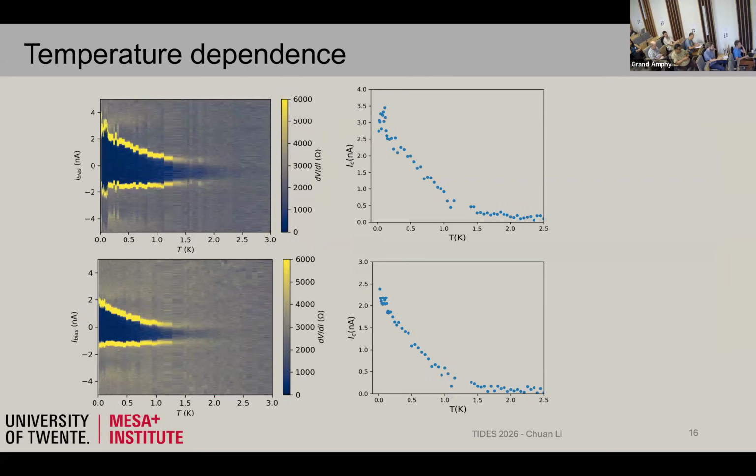And I think one of the funniest things we measured is this temperature dependence. So with such a little critical current, you can see it's about 4 nanoamp. The system is pretty robust, here it comes a little lower, but still up to 1.5 Kelvin we can still measure this supercurrent quite clearly. And if you go a little bit into the detail, there's no saturation at lowest temperature.